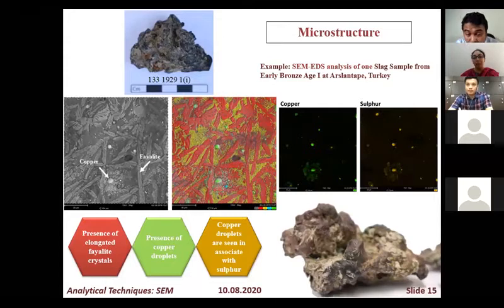So we can predict in this way: our XRF result, XRD and SEM complement each other, and we can know that our slag sample is a copper-based slag, and it also has the fayalite, so it's the product of smelting activities. And this slag may also be related to a sulfur-based mineral.